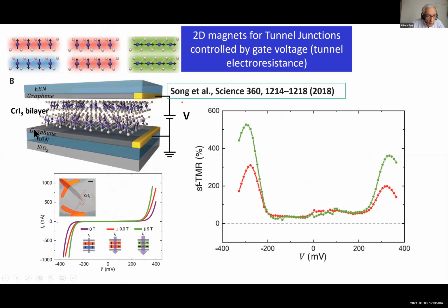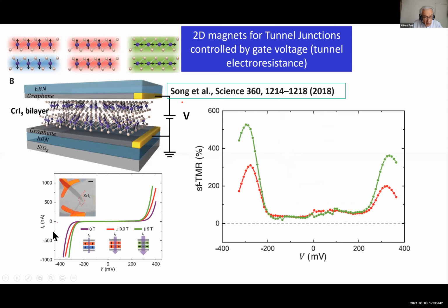And so between the electrodes are graphene, and below there is a layer of hBN. And in fact, what has been found from this theoretical calculation is that by applying a voltage, it's possible to reverse the magnetic configuration from anti-parallel to parallel, is what is occurring here. By applying a voltage between the two electrodes, the system reverses, it becomes ferromagnetic instead of anti-ferromagnetic. And at the same time, you can see the current increase, the conductance increase a lot.